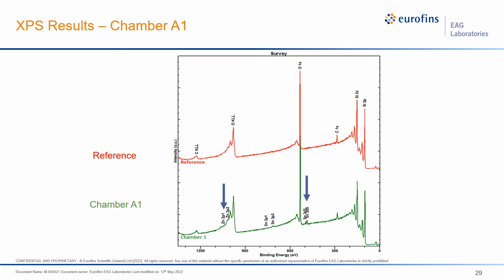So this is a result on our chamber A1, which was the most interesting one from the XPS. Our reference silicon wafer has silicon, carbon, oxygen. The carbon and oxygen you'll wind up on almost every sample once you expose them to air. The chamber A1 actually had residues of tin and zinc on the surface. So having tin and zinc floating around in your chamber is not good. So this was actually very surprising to us, but this was something we wanted to let them know. This is actually on a chamber where they had been doing some adhesive work in the past, and they wanted to know if they could then use this as a reliability test chamber. And based on the zinc and the tin alone, I would tell them they need to have a good cleaning before they start doing that.